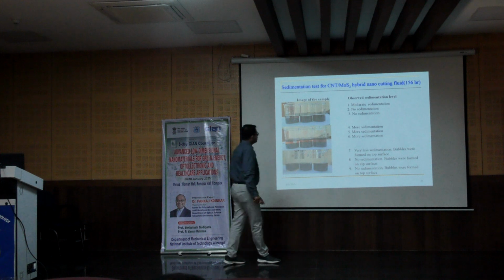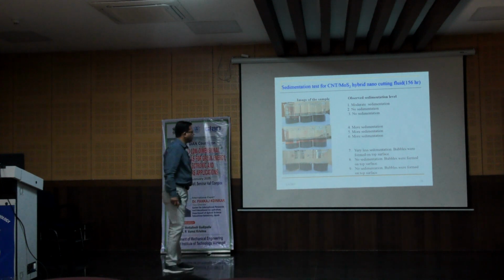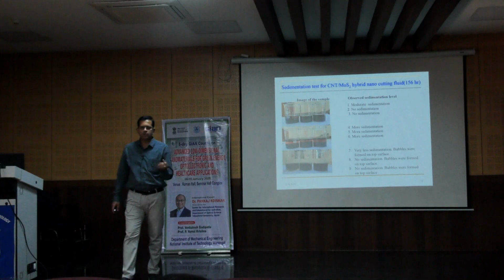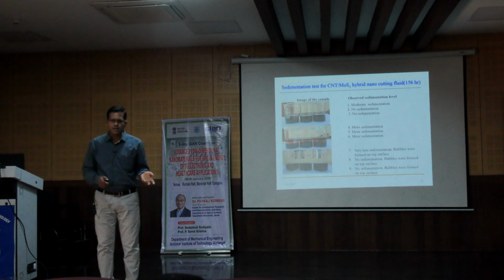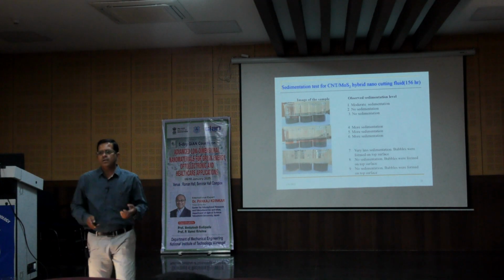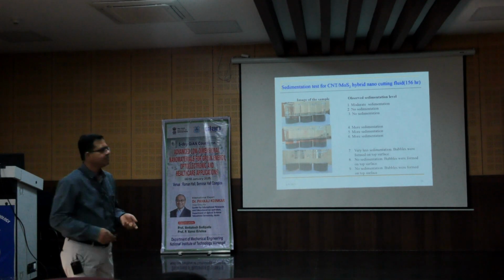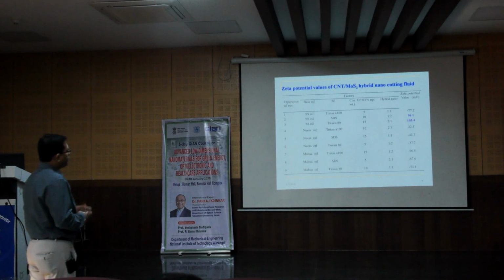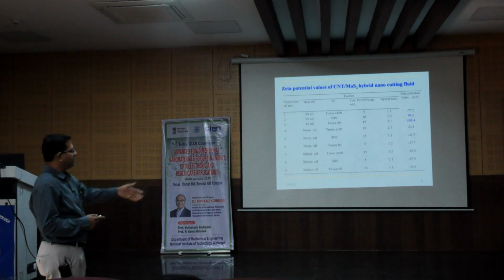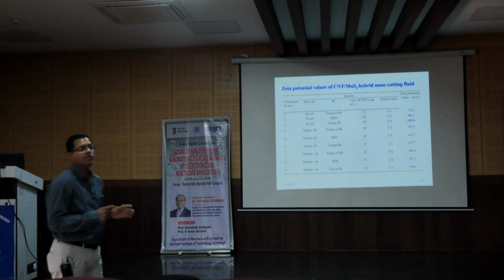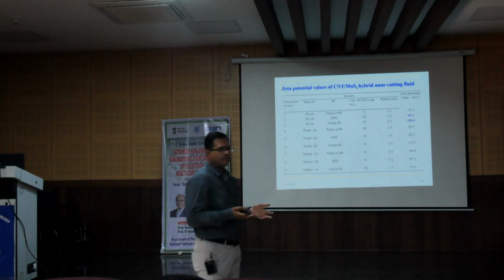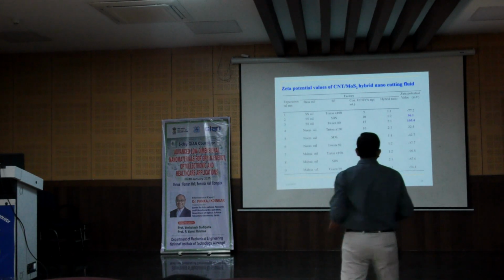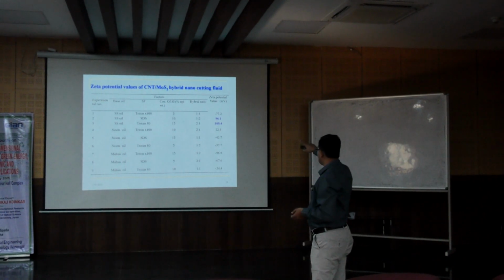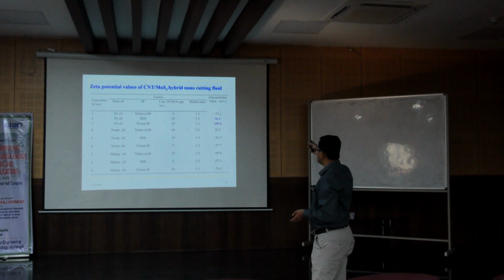But sometimes even though sedimentation is not there, we observe some bubbles or some type of reaction, etc., which may not be suitable for our cutting fluids, right? So after that we again verified the zeta potential values. Where we got a high zeta potential value, that is more than 60, these two are higher values, and we have some negative values and some positive values. Both are okay, right?